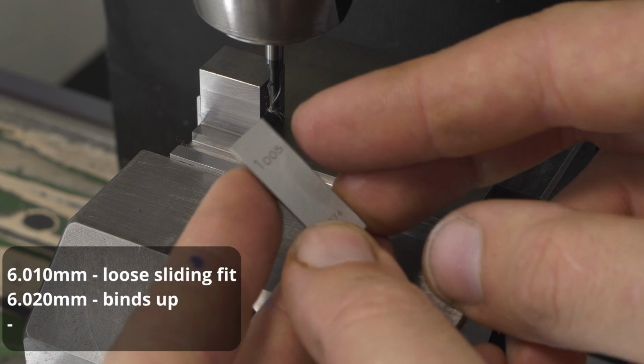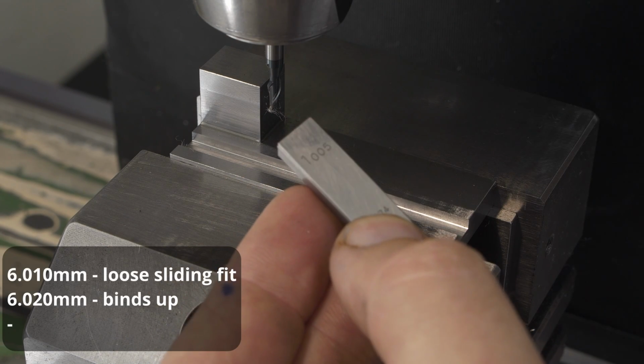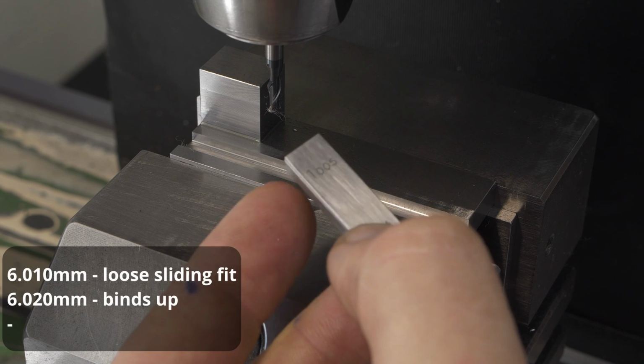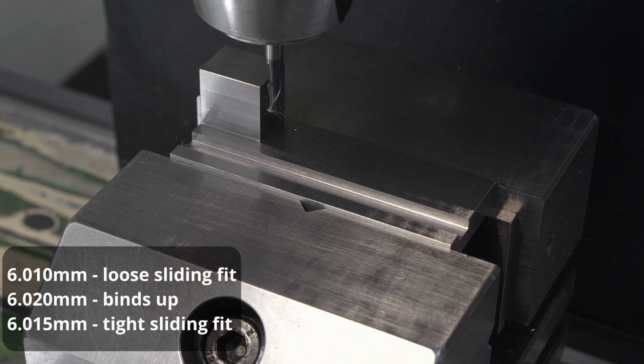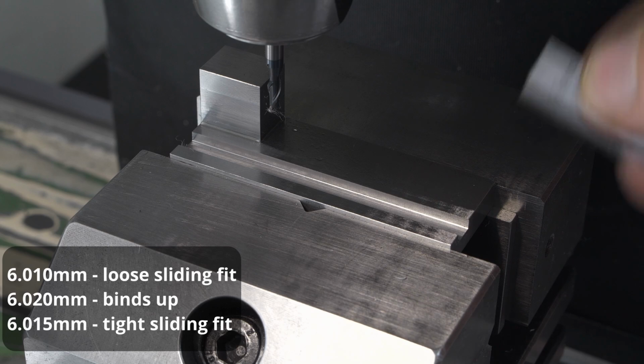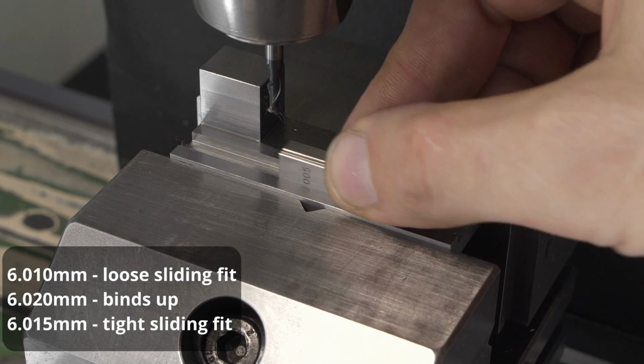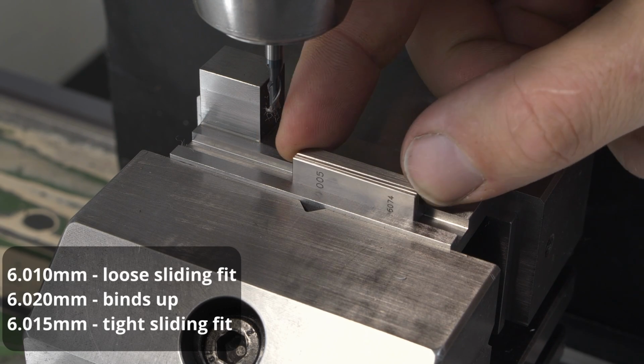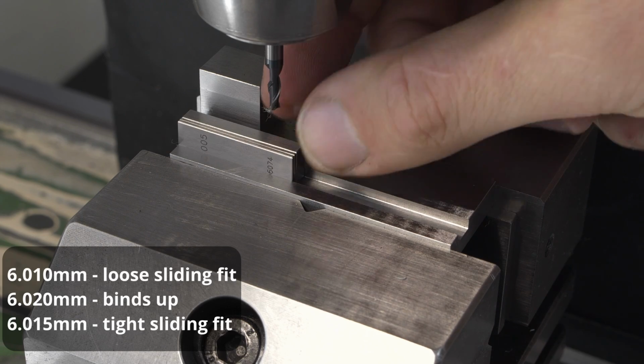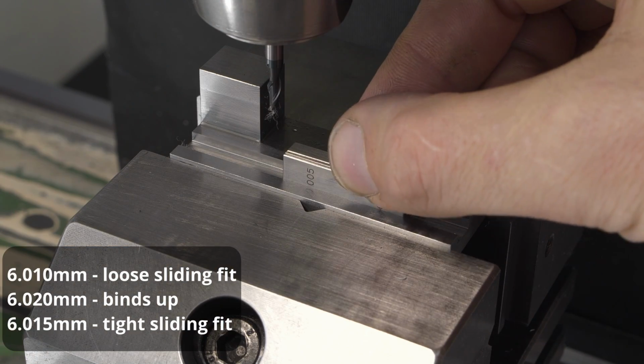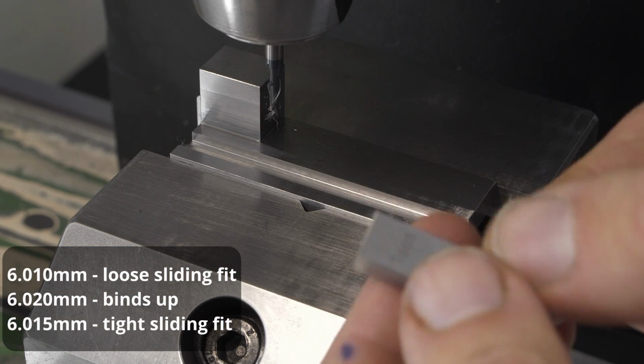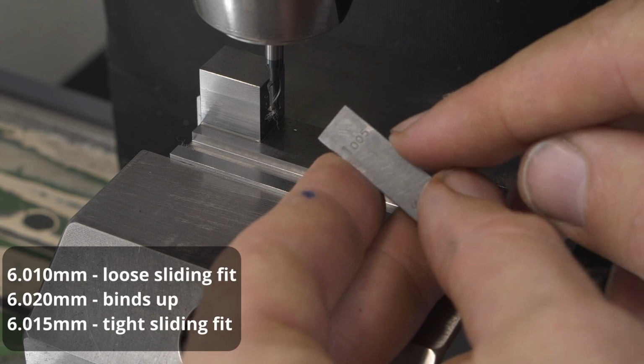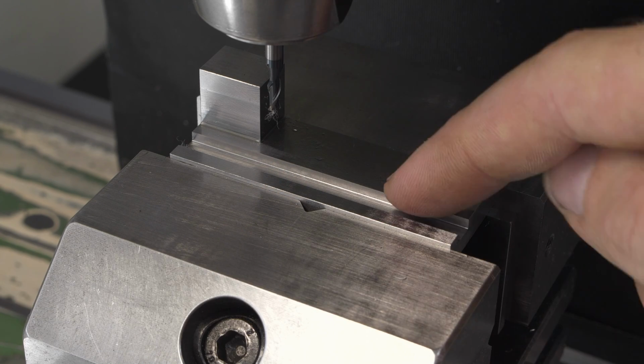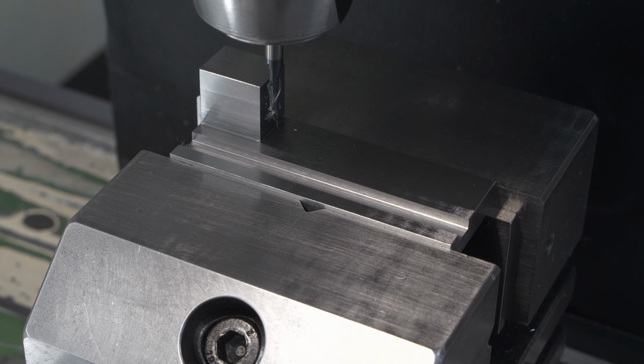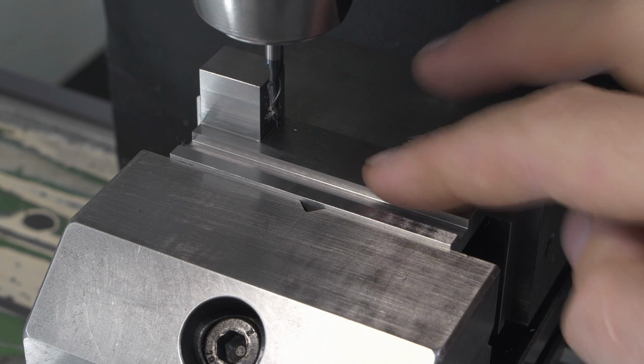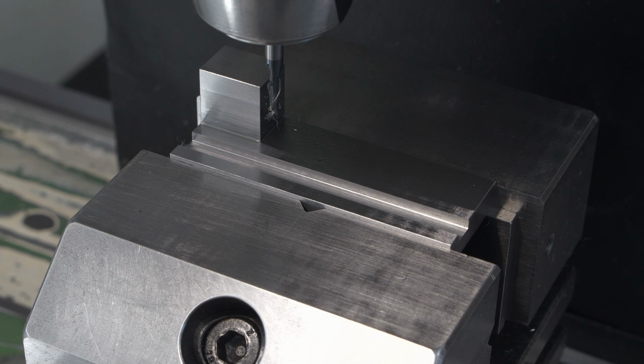I also built a gauge block stack with 6.015 millimeters, 5 micron larger than my small gauge block that I had before. And this is an extremely tight sliding fit with barely any wiggle. So 5 micron more than this, and it doesn't fit anymore. Just to give you an idea of how tight the slot is and fit.